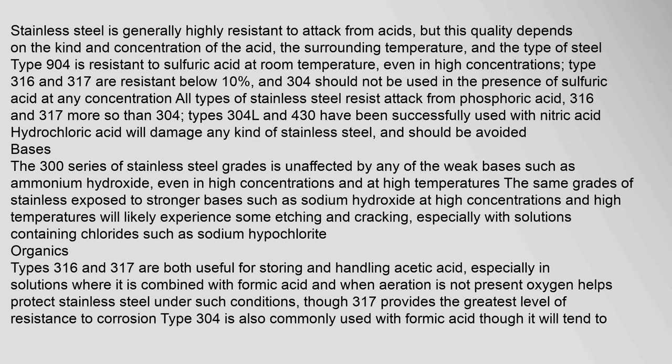Stainless steel is generally highly resistant to attack from acids, but this depends on the kind and concentration of the acid, the surrounding temperature, and the type of steel. Type 904 is resistant to sulfuric acid at room temperature even in high concentrations. Types 316 and 317 are resistant below 10 percent concentration, and 304 should not be used with sulfuric acid at any concentration. All types resist phosphoric acid. Types 304L and 430 have been successfully used with nitric acid. Hydrochloric acid will damage any kind of stainless steel and should be avoided.